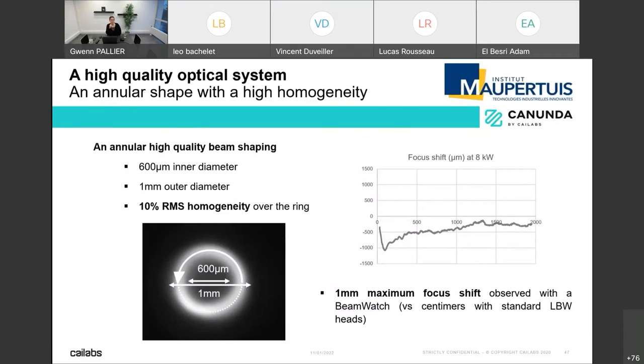I'll try to take some time to explain why we use one shape for one process, because it's very important. The idea is that you have your keyhole. The keyhole is where your material is melted and where you will actually be doing your weld. It is sometimes unstable, and that is a limitation of the process. When you have a ring of that dimension, 600 micrometer inner diameter, 1 millimeter outer diameter, you try to encircle the keyhole to stabilize it, and it's actually working very well. The idea is that you will follow the keyhole with your ring, and you will stabilize it inside the ring. So we are having a very high quality.